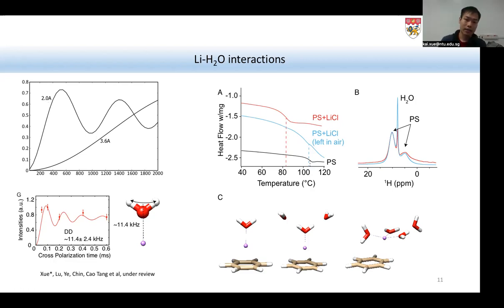So I verified this interaction is more driven by charge affinity, and gave this model to my DFT collaborator. They put it into simulations and found that by adding water to the system, the cation-pi interactions between lithium and the aromatic ring can be quenched once the water number exceeds 4, because the water-to-lithium interactions are so strong, they actually quench the cation-pi interactions between lithium and the aromatic ring.